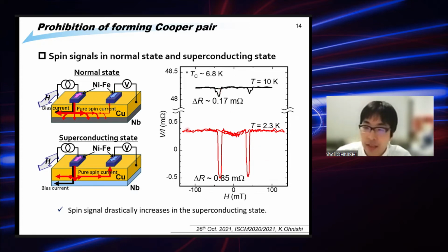On the other hand, the red line indicates the superconducting state. We measure the superconducting state at a temperature of 2.3 Kelvin. At that temperature, the spin signal is 0.85 milliohm. Obviously, the spin signal drastically increased in the superconducting state.